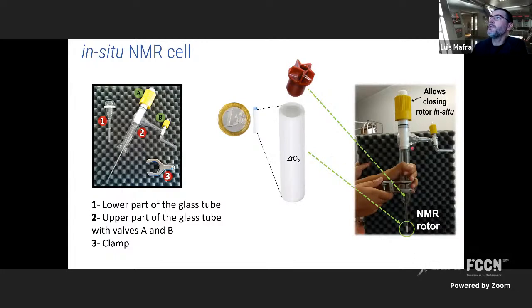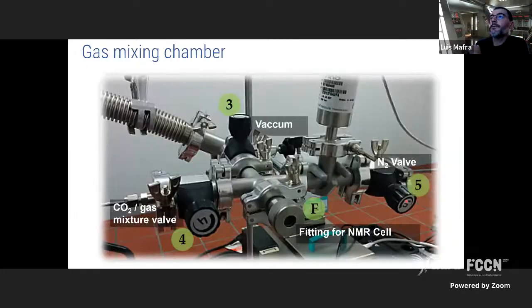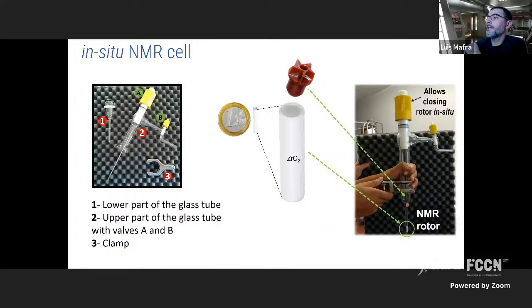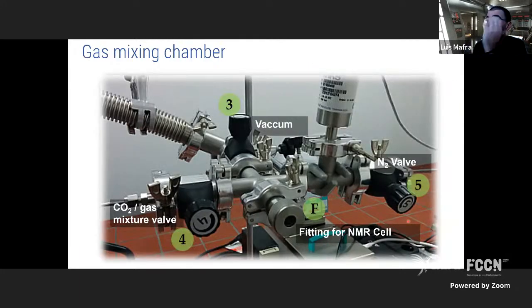And we have built an in situ NMR cell where you can close it with a clamp. We put a cap on the bottom part of a metal piece here, and then we just degas the sample first. Okay, once it is degassed, we can admit any partial pressure of gas that we wish. Okay, we wait for equilibrium to be reached, and then we are ready to mix other gases as well if you want. Okay, so with this done, we just close the cap inside, still with controlled environment, and then we just run to the NMR magnet to do our analysis.